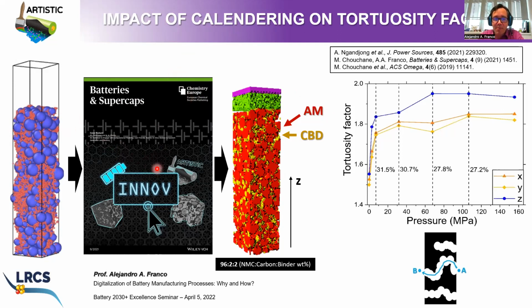And you see that when you apply this voxelization technique or this meshing procedure to these electrode microstructures predicted from the calendering, you get electrode microstructures that don't look anymore like a collection of spheres. They look more like a real tomography image of an electrode, right? Which is very nice, right? At the end of the day. Then what you can do with this is you can inject this in a software.